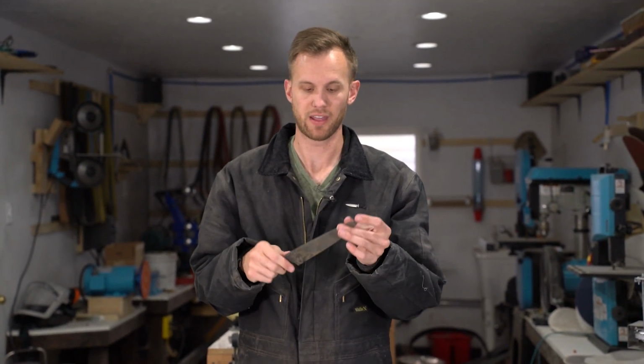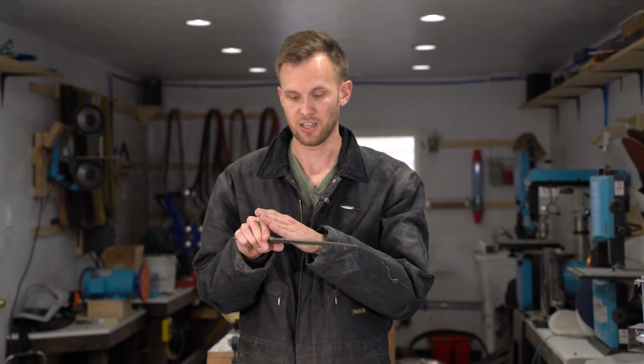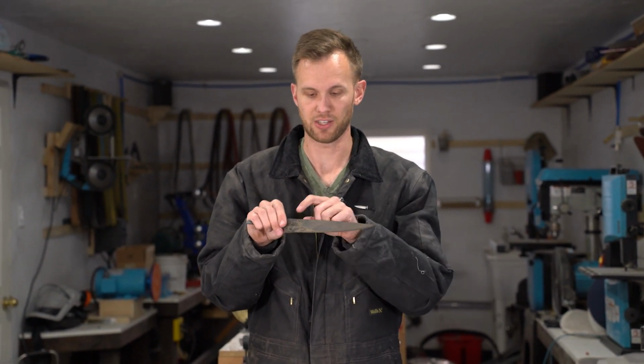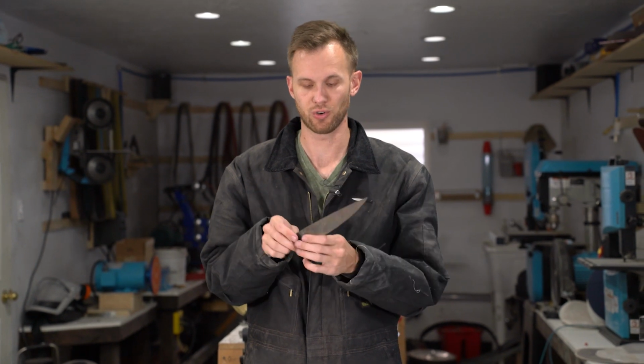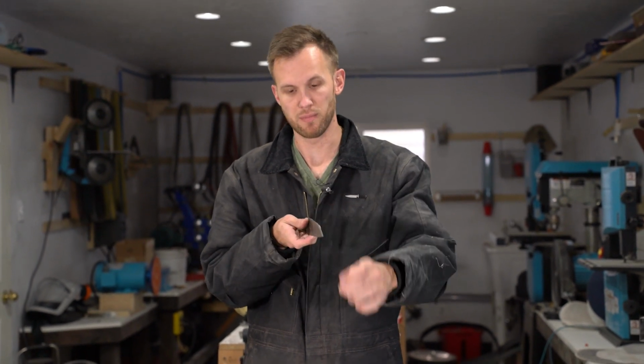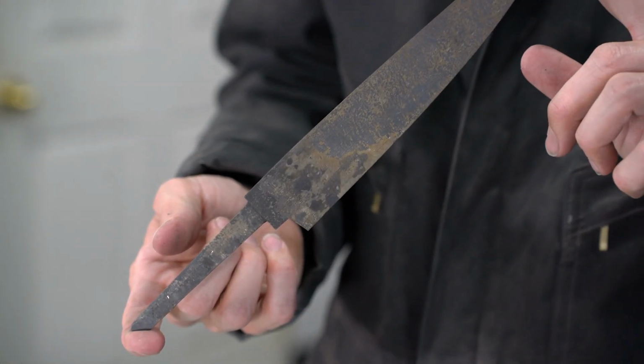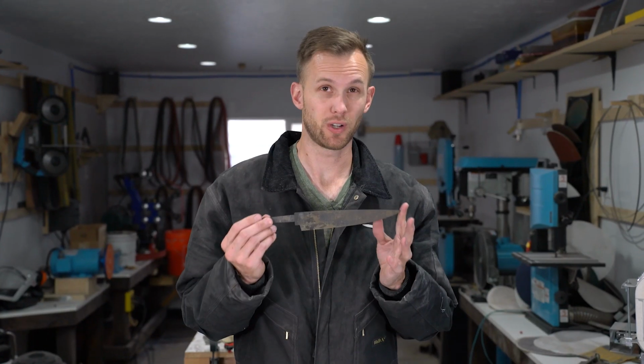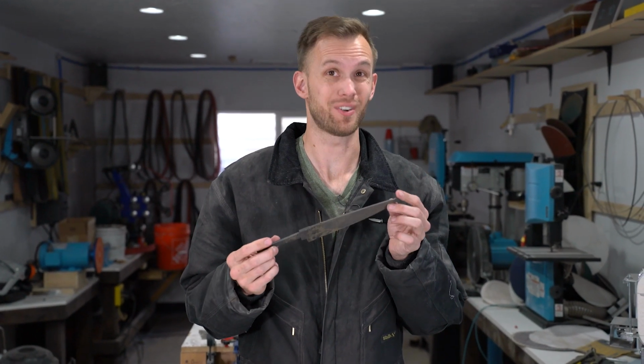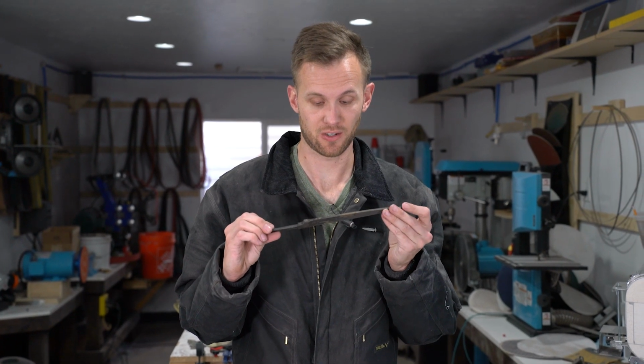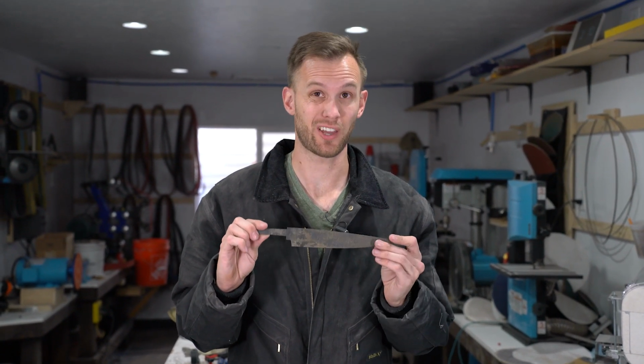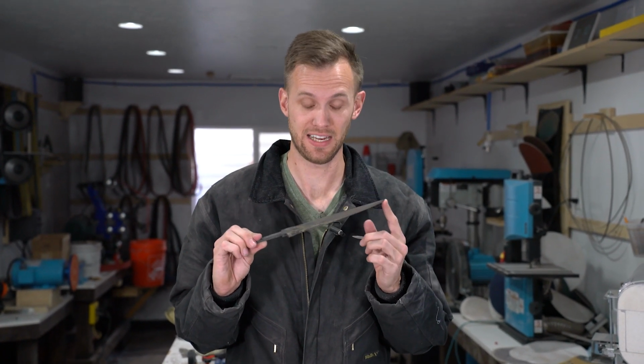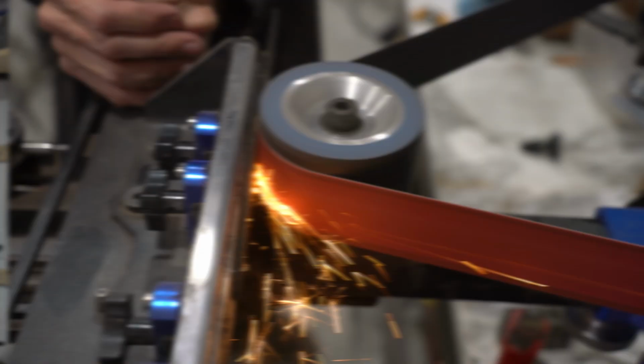I think we'll start by throwing it back in the surface grinder, taking off a lot of this scale and making sure that the blade really is straight and true. Then we can take some measurements of where the middle is and start grinding down to actually put in the bevels on our blade. After doing all of the heat treating and tempering, all 3 cycles of it, I did another test on our hardness tester, and this thing still came out at an HRC 59, so this is going to be a very good, hard, probably quite tough blade.